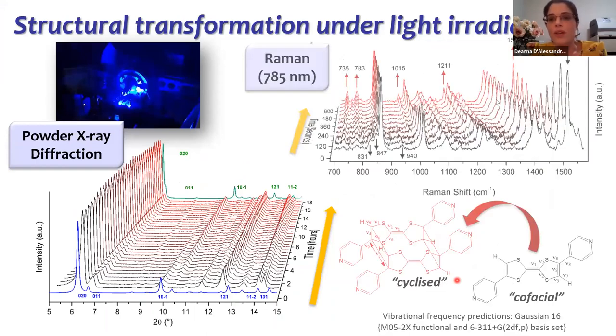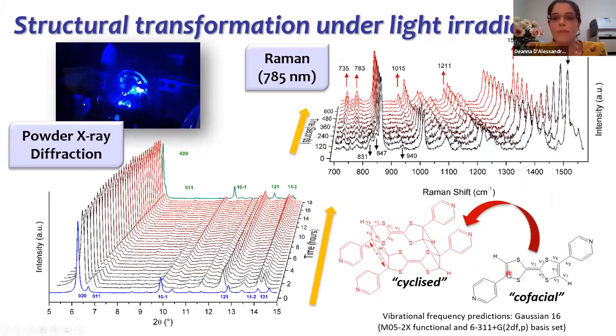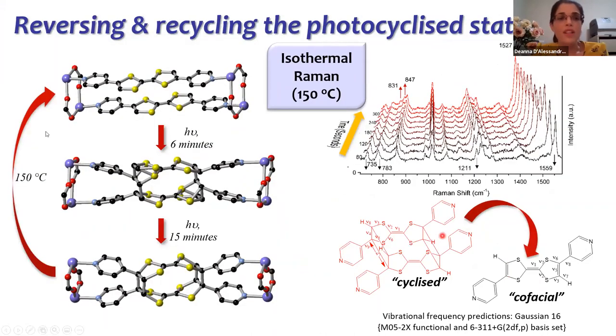And we can also follow it using light irradiated Raman spectroscopy as well. So here in particular, we can follow the carbon-carbon bonds at the back end of the TTF, and we can watch them as they undergo that photocyclization and alter their vibrational frequency. And this is all corroborated with computational data as well. What is nice here is that if we heat this up a little bit, we can reverse this, and this is done at about 150 degrees, and we can cycle this around 3 times. If we try to do it any more, we do see structural collapse of the crystals.